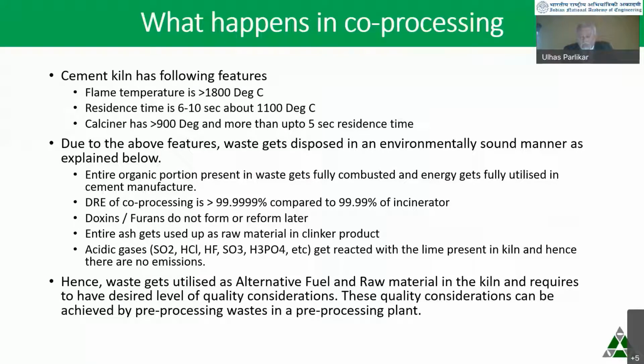So even if there are some amounts of heavy metals present in the waste streams, it is not a cause of concern at all. Only causes of concern are two. One is chromium 6, because it is very labile and it is leachable. So we ensure that chromium 6 is not entering the cement kiln. And the second one is mercury, because mercury is volatile. And this mercury has the potential to rise and then leave from the stack in a volatile state. So therefore, we have an input control on mercury and chromium. Most of the other heavy metals are easily trapped.